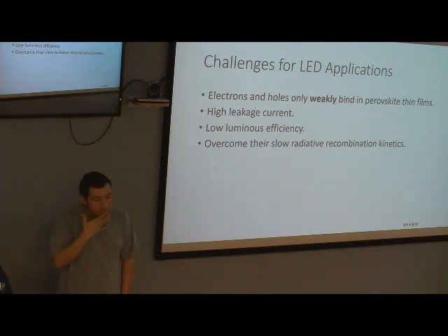Well, in one of the papers that I read, when they tested the luminous efficiency of the perovskite, they ran it against 60 devices. The champion device, or the best efficient device, where the external quantum efficiency was the highest, was 14.3%, but they were getting some as low as about 12%, 10%. They had a histogram of it, but the highest they found was 14.3%.